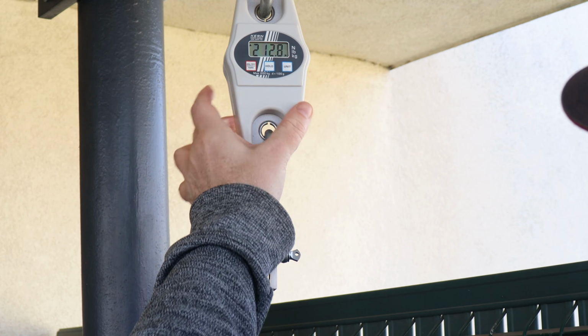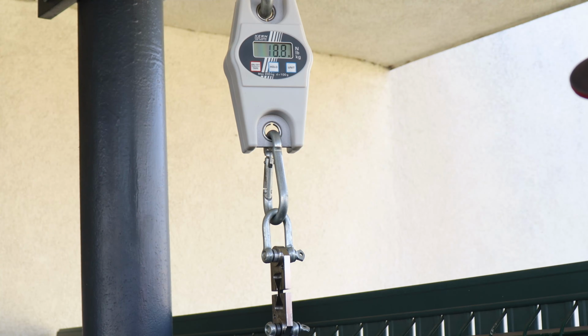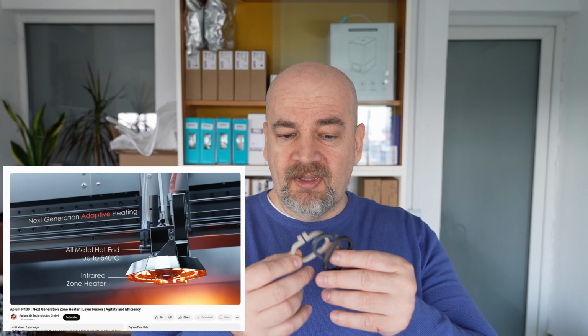Now some conclusions. On one side it is very strong material in the creep, tensile, bending test, but somehow I cannot really like any filament which has weak layer adhesion. These 20 kilograms are on the edge of the acceptable, but especially from this filament I was expecting more because of the zone heater and remelting of the top layer. I will see if the Vision Miner will have similar layer adhesion. If yes, then that's it, possibility of the PEEK.